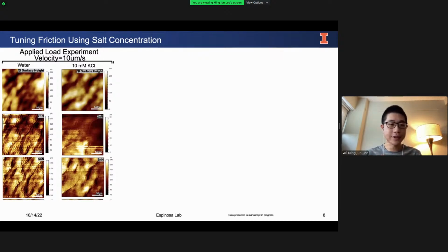What I'm showing here, on the first row, is the height channel of the quantitative imaging images that I showed earlier. And then from the second and third row onwards, these are friction maps, so direct visualization of the friction force on the surface of the hydrogels. The first experiment I'll be showing is the applied load experiment, where I have fixed the sliding velocity of the AFM tip to 10 microns per second.